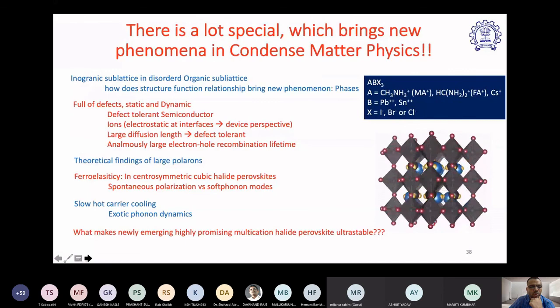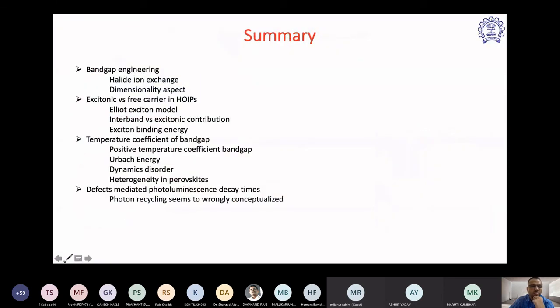So this is what I was telling, that lots of exotic phenomena happen. These are the things I was saying, that band gap engineering in halides can be done by halide ion exchange or by changing the dimensionality, n equal to 1, n equal to 2, n equal to 3 layer. Further, we have excitonic character and we also have free carriers. If you have iodine, you have free carriers. If you have bromine, you have excitonic character. If you have chlorine, you have much more excitonic character. Those excitons can be fitted using Elliott's model. We can determine the interband versus excitonic contributions by using this optical model of the excitons.